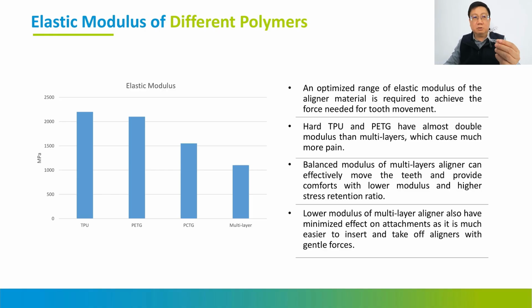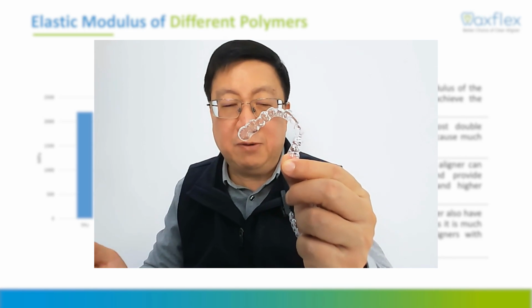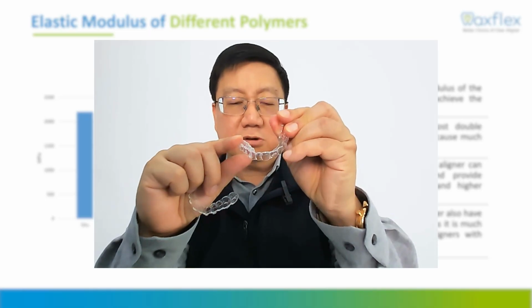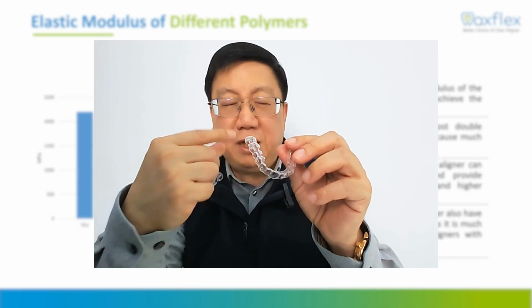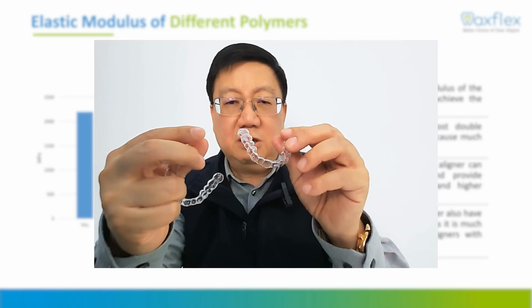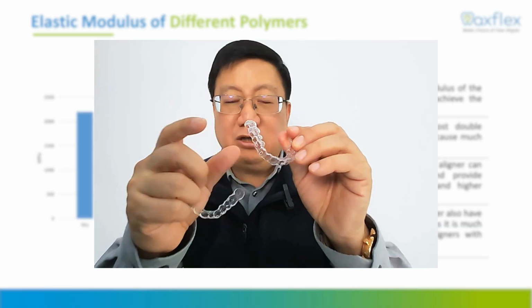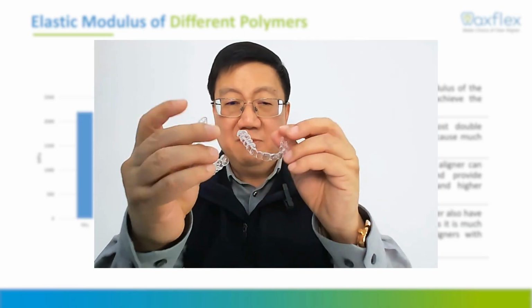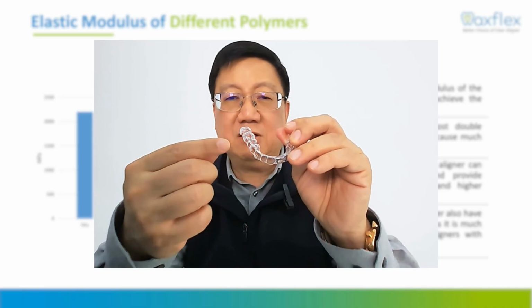I'll show you two products. This is the retainer material, based on polyurethane, 100% polyurethane single layer for retainer. This is the multi-layer based on the PTP structure: polyethylene, copolyester on the outside and the softer TPU in the middle. Let me show you the difference. You can see this is very rigid. Normally the problem is that the patient or the operator, even dentists, think this is harder. But actually the thickness is exactly the same. You feel it is thicker because its modulus is higher.